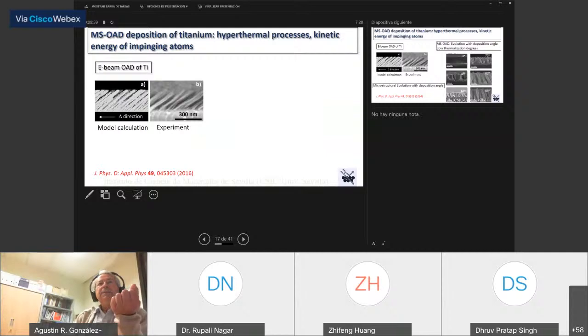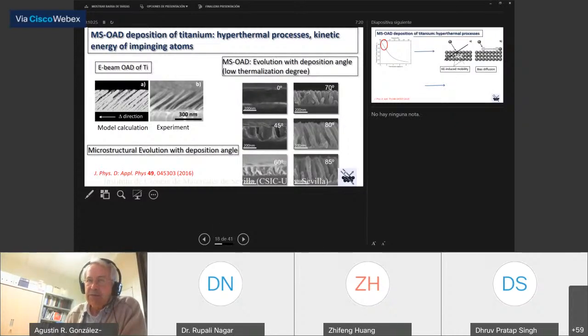Thermalization degree is important, but also the energy of the deposition particles. Well, this is a simulation, electron microscopy characterization and electron beam evaporated titanium. So you can see here that this is the typical situation when we work with a punctual source as in electron beam deposition. However, if we do the same experiment in magnetron sputtering, what you can see here is that we get nanocolumns when we work at very tilted angle, but nanocolumns which are completely different than the nanocolumns that we obtain by electron beam evaporation.